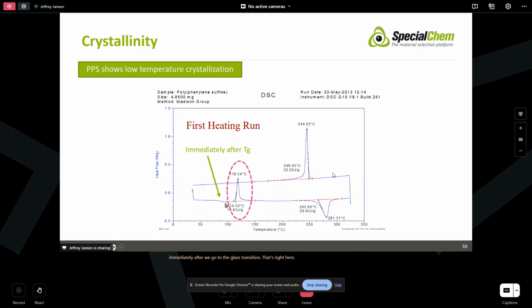Once we go through glass transition, those molecules have sufficient freedom now that they can reorganize themselves. They're not locked in anymore, not as much. And so they can reorganize and they form some crystals. And that's what we're seeing here, is this material forms crystals. When we see that, my immediate thought is, well, that material's been undercrystallized through the injection molding process. The material wants to be more crystalline. Okay, not 100% crystalline, obviously, but it wants to be more crystalline.